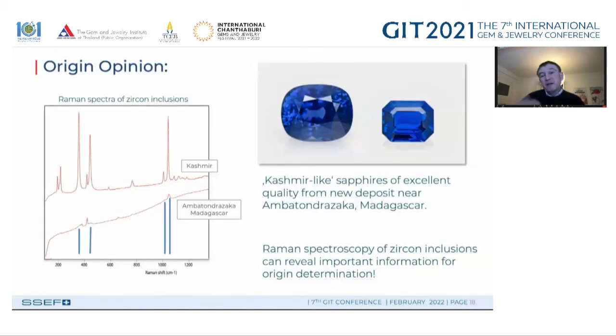But then we also have access to look, for example, at the structure of inclusions. What we have here are two Raman spectra of zircon inclusions in sapphires. And as you can see, there is a huge difference between sapphires from Madagascar, like Ambatondrazaka, where you have a very metamict zircon inclusion, so very broad peaks, compared to Kashmir, which shows very narrow and well-formed Raman peaks. So this is a very useful way to separate these stones, even if they visually look very similar.